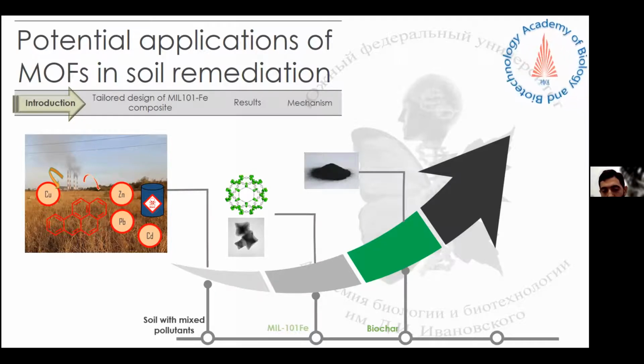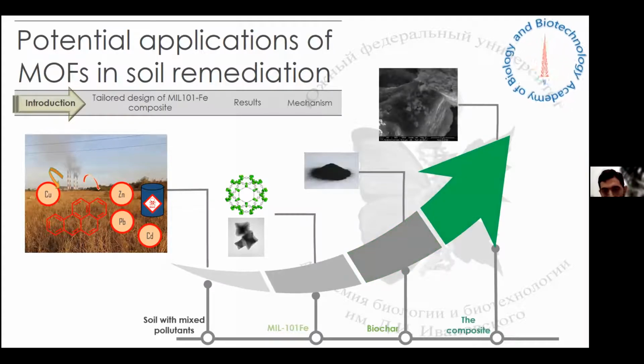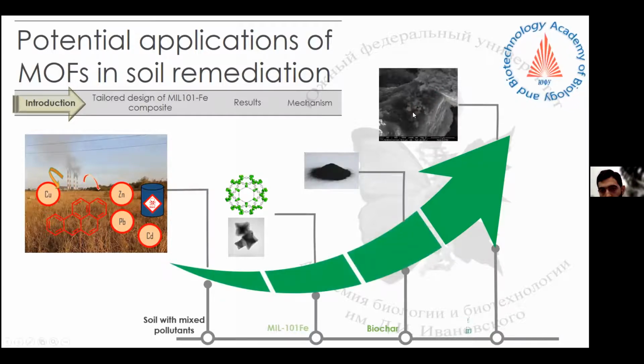So the second step was that we decided to composite our metal organic framework with biochar to introduce our material inside the soil. You can see a photo of the composite that we synthesized. Here is biochar, and you can see MIL-101 evenly distributed on the surface. So it was our strategy to be the first group of researchers to use the metal organic framework in soil remediation.